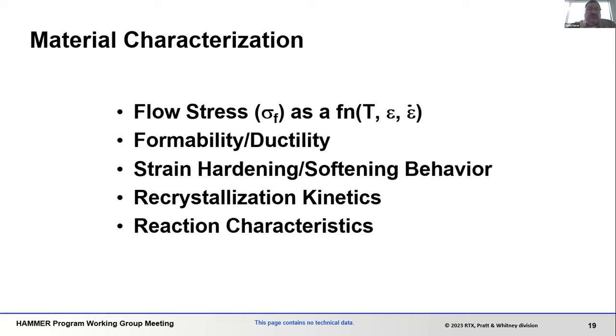So some of the material characterizations that need to be done: you need to look at the characteristics, flow stress, and flow stress as a function of temperature, strain, strain rate. Formability, the ductility of the material, strain hardening or strain softening behavior, recrystallization kinetics, and reaction characteristics as well to the process. If you're doing it at low temperatures, does it have spring back? Are you generating residual stress due to non-uniform strain, et cetera?